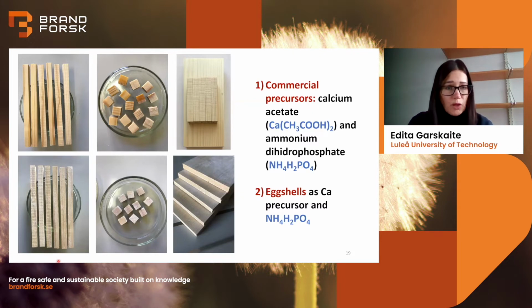So what we did, we prepared samples of different sizes. These were used for mechanical properties, bending. Then we also had samples which we used for compression strength testing. We had bigger blocks which we used for cone calorimeter, and for all other characterization techniques we used any of these samples and checked the saturation of this wood, how this material precipitates in situ. So we performed from commercial precursors, where we used commercial calcium acetate and ammonium dihydrogen phosphate, and we also used eggshells as the calcium precursor, and then we used the same ammonium dihydrogen phosphate.